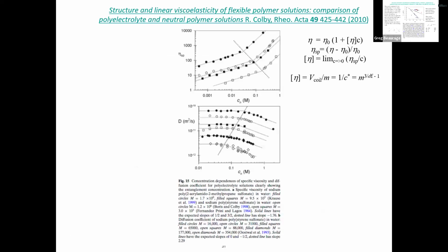So that's basically what this equation says. This is just a displacement equation. The volume of these blobs, concentration divided by that tells you how many blobs. That's going to boost the viscosity of the solvent because you displace the solvent with the blobs. Right, so linear sum displacement law.